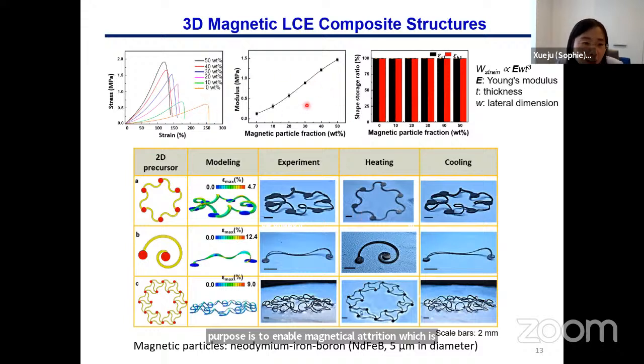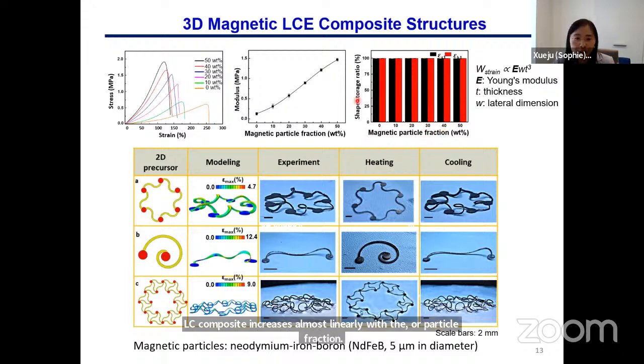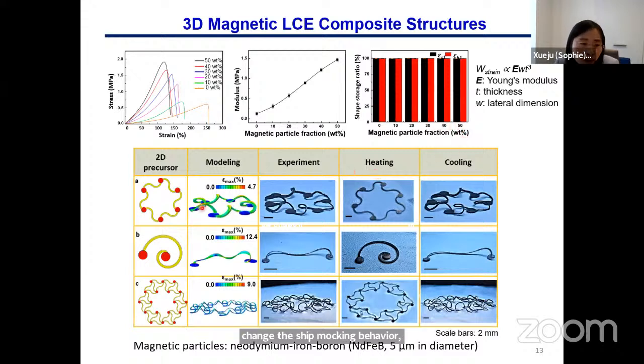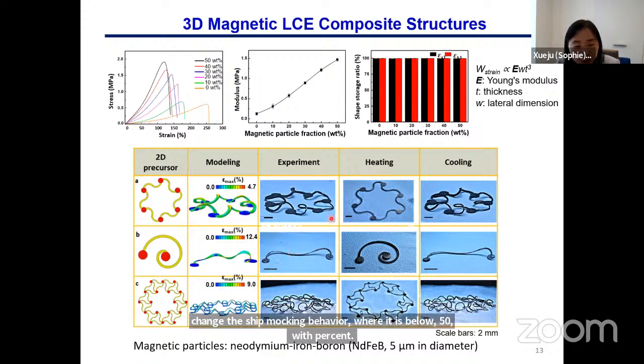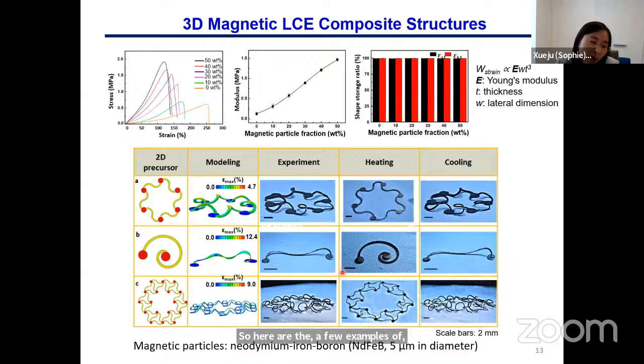So we can see that the modulus of the magnetic LCE composite increases almost linearly with the magnetic particle fraction. Also, we showed that adding magnetic particles does not change the shape morphing behavior when it is below 50 weight%. So here are a few examples of magnetic LCE composite structures which are very compliant and inaccessible with the pure LCE materials.